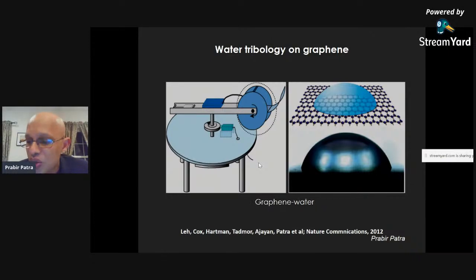So we thought that means what we're essentially creating is a very nice surface where graphene molecules are not getting a chance to reorient or intermolecular change of that. Hence, we are creating a very low lubrication surface. So now you can make, let's say, you can anchor certain molecules on graphene, and then put the water droplets. It might not spread that fast, but slow. You're creating a gradient-based friction on a surface.